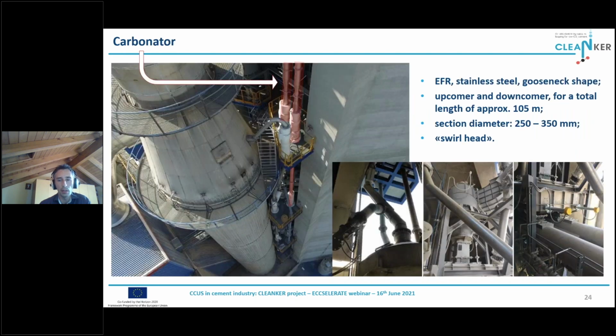Here you have the carbonator, which is an insulated stainless steel gooseneck reactor. It is a very long reactor for the reasons I explained before. So it is more than 100 meters, and this length is basically needed to ensure the residence time required to obtain a significant advancement of the carbonation reaction, so ensuring to reach significant carbon capture rates. We also have a variable diameter. Indeed, in the downward section of the carbonator, the diameter is larger, and this is again to reduce gas velocity and to increase the residence time of the particles.